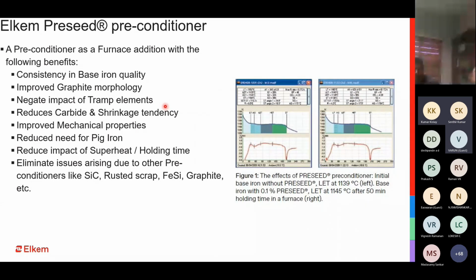This is what I'm talking about, the foundry conditions. It can have a layout, a kind of setup where you do need to hold the metal, or you do need to superheat the metal, and that is where the impact can be reduced by the addition of a preconditioner. It does eliminate issues which can arise due to other preconditioners like silicon carbide, rusted scrap, ferrosilicon, graphite, etc. So these additives also work as a preconditioner, but they bring their own set of problems with them.